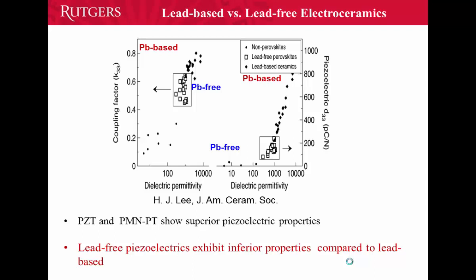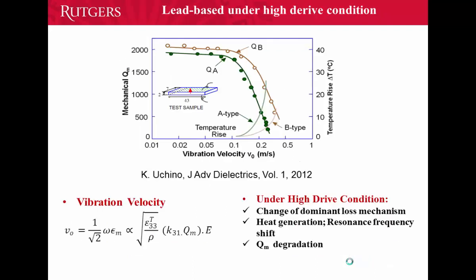And the piezoelectric coefficients for lead-free materials are between 18 to 300. However, the lead-based compositions show very high piezoelectric coefficients, up to 800. So we could say that under low drive conditions, the lead-free piezoelectrics exhibit inferior properties compared to lead-based materials. But we should consider that under high drive conditions, the performance of materials will change.